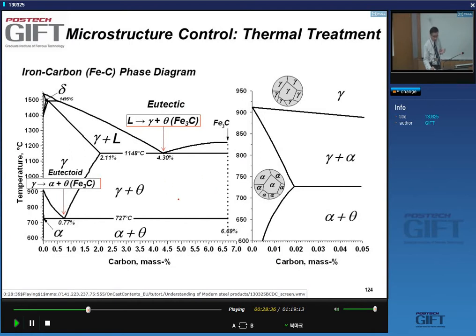This is the steel that you just saw, yes? If I want to indicate it on this diagram, actually I cannot, because it's located somewhere here. On this scale of things, the steel composition of the example I just showed you is somewhere hidden here. So I need to blow this up, and then I see that close to the y-axis, I actually have a domain of stability for ferrite containing carbon. This is pure single-phase ferrite containing carbon.